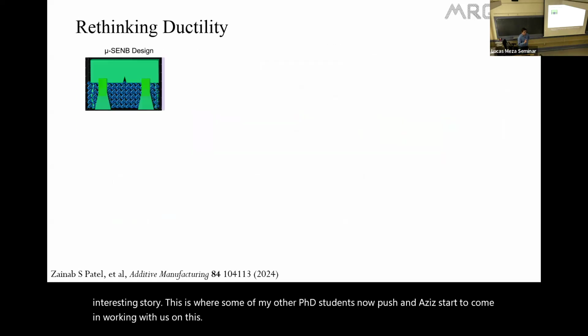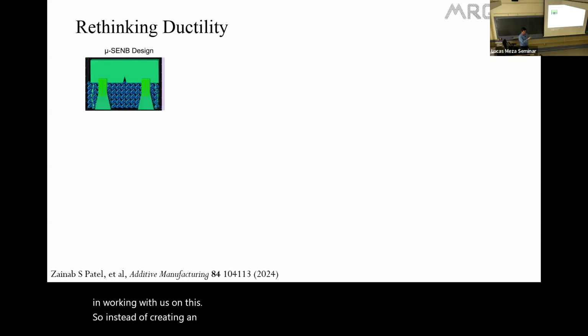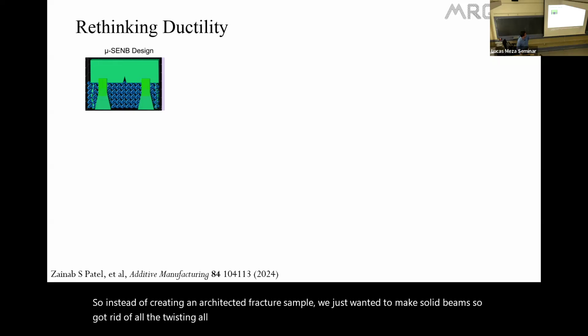So instead of creating an architected fracture sample, we just wanted to make solid beams. So we got rid of all the twisting, all the layering, and made these solid single edge notch beams. In the printing process, we can control laser power.